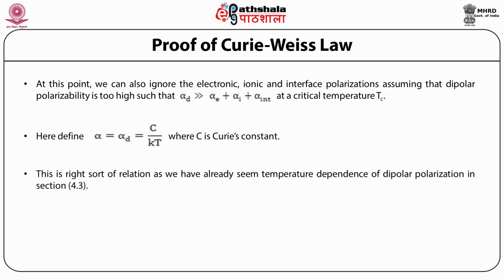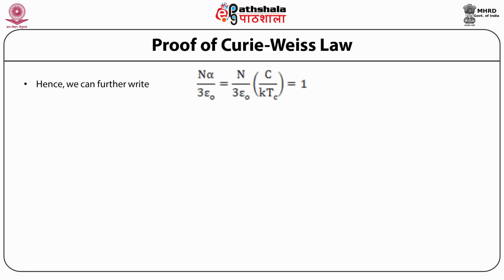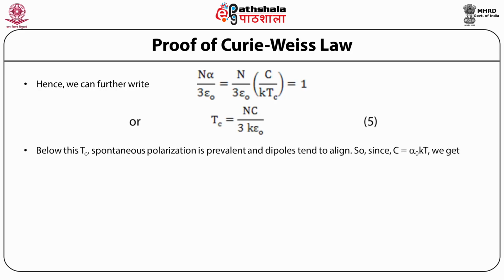And this is the right sort of relation, as we have already seen the temperature dependence of dipolar polarization in the previous sections. Further, we can write that n alpha upon 3 epsilon naught is equal to n upon 3 epsilon naught into C by kT is equal to 1. So, Tc is equal to NC upon 3k epsilon naught. Below this Tc, the spontaneous polarization is prevalent and the dipoles tend to align. Since C is equal to alpha naught kT, we get Tc as n alpha T by 3 epsilon naught, or Tc by T is equal to n alpha upon 3 epsilon naught.